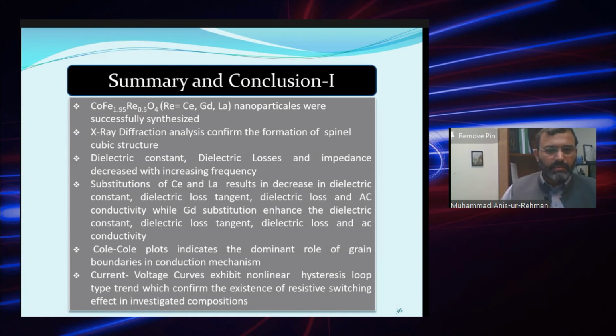So, concluding the first section, nanoparticles were successfully synthesized. X-ray diffraction analysis confirmed the formation of the spinel cubic structure. Dielectric constant, dielectric loss and impedance decreased with increasing frequency. Cerium and lanthanum result in a decrease in the dielectric constant, while with gadolinium there was an enhancement in the dielectric constant. The Cole-Cole plots indicate the dominant role of the grain boundaries in the conduction mechanism, and current voltage curves exhibit a non-linear hysteresis loop type, which confirms the existence of the resistive switching effect in the investigated compositions.